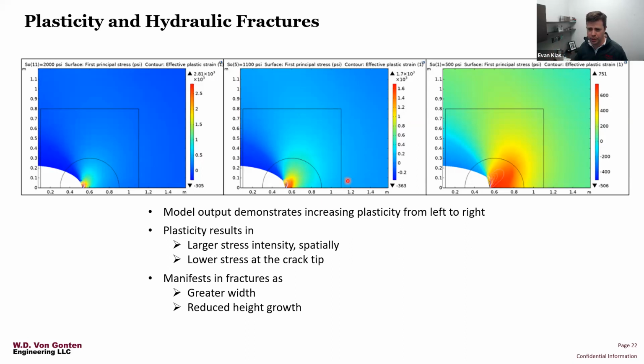You'll notice the stress concentration created at the fracture tip is more largely distributed spatially. The plastic deformation occurring at the fracture tip is actually blunting the tip and reducing that stress concentration, and through that, the stress at the fracture tip itself is also decreasing.